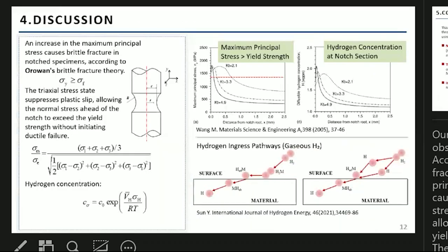Our discussion ties this observation to established theory, according to Orowan's brittle fracture theory. High maximum principal stress at the notch root can cause brittle fracture. But the constraining stress state suppresses plastic slip, allowing the stress to exceed the yield stress without ductile failure. And the distribution of hydrogen in the material is closely related to the hydrostatic stress. And these two figures here show the distribution of maximum principal stress and diffusible hydrogen concentration across the notch section.